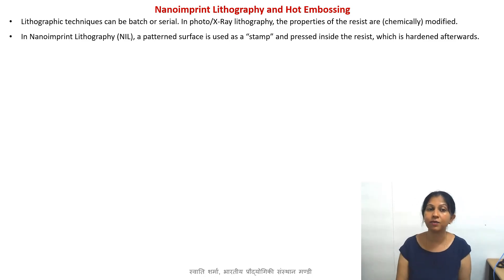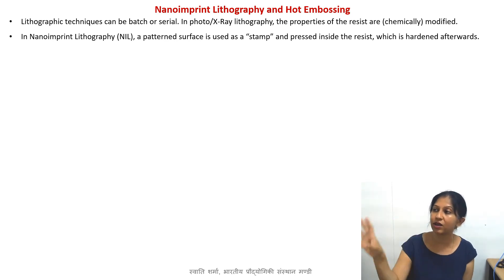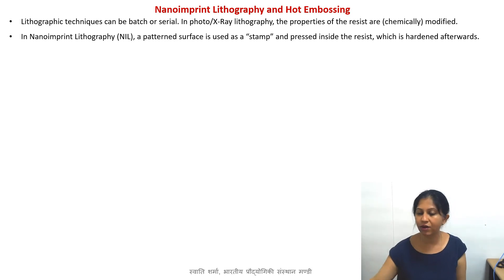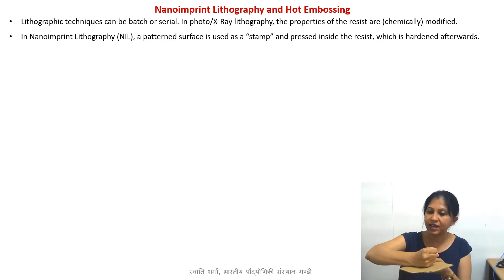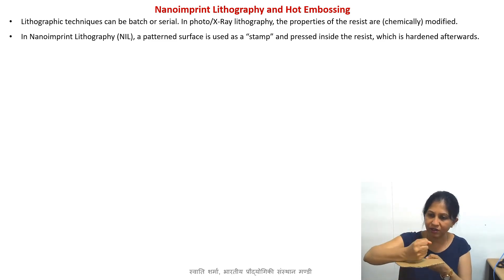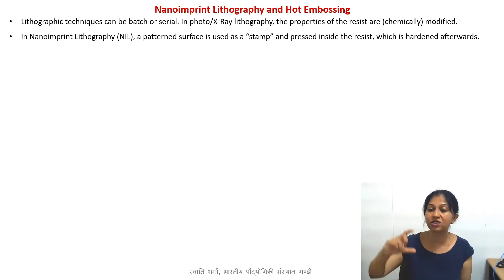This is what is done in nano imprint lithography and hot embossing: you make a stamp with your structures on it — similar to writing your name and printing it on paper. You have a film of polymer spin-coated onto a silicon wafer or any substrate, then you take the stamp and press it in while increasing the temperature to slightly above the glass transition temperature of the material, so the stamp slowly sinks into the softened polymer. Viscosity must also be optimized, because if the material is too viscous the stamp will not fill the structures fully.